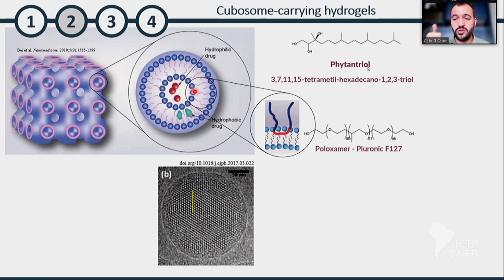So it's good to host both hydrophobic and hydrophilic components. And it's made of phytantriol. There is a straightforward recipe. And it's made kinetically stable by a copolymer, a PEO, polyethylene oxide, polypropylene oxide, polyethylene oxide copolymer, right? So it's a real cubic phase, and it's good for hosting molecules of different chemical features.